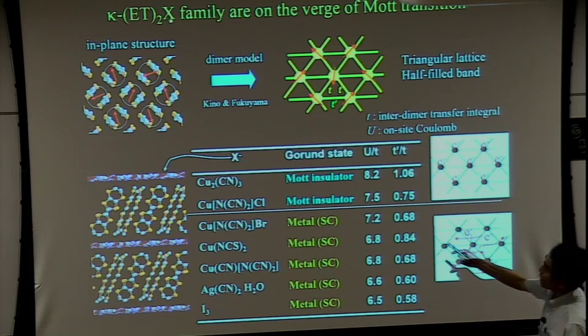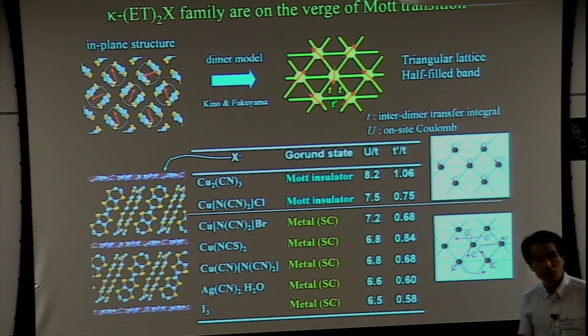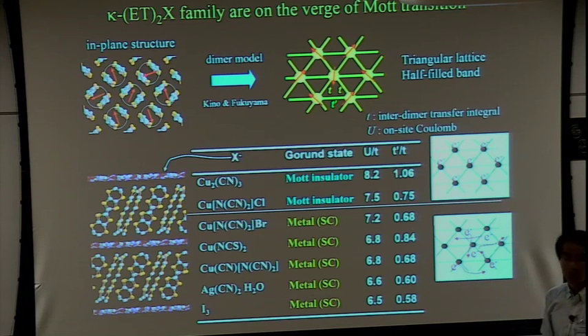X has a valence of -1, meaning one electron is absorbed from these ET layers. This means ET2 has a hole of +1. So this dimer has one hole, meaning one lattice accommodates one hole. This is effectively a half-filled band. So this material is modeled as an anisotropic triangular lattice with a half-filled band.